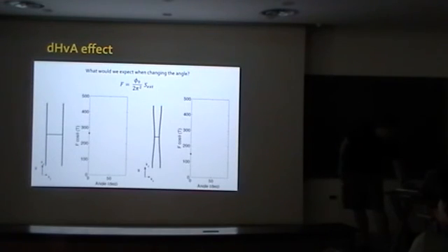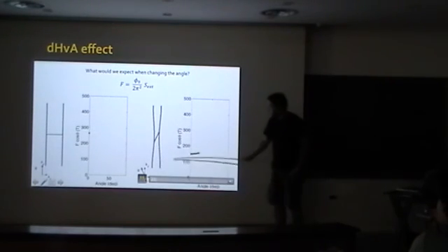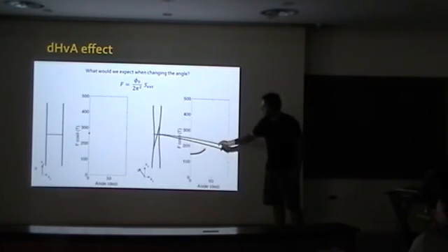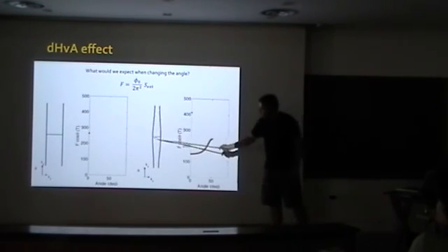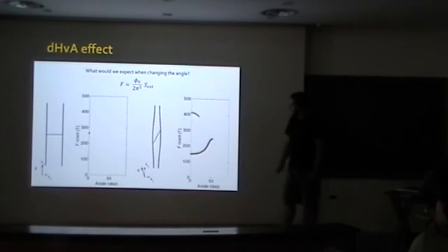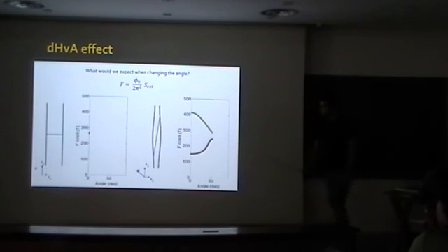Now if we do the same thing with a Fermi surface that's slightly warped in kz, then again we do not have this perfectly cylindrical shape. So what we see is a deviation from the straight line that we had on the other side. For the minimal orbit, we get an upturn in the frequency times cosine theta, and for the maximal orbit, we get a downturn. So this is what it would look like in terms of how our frequency changes with angle.